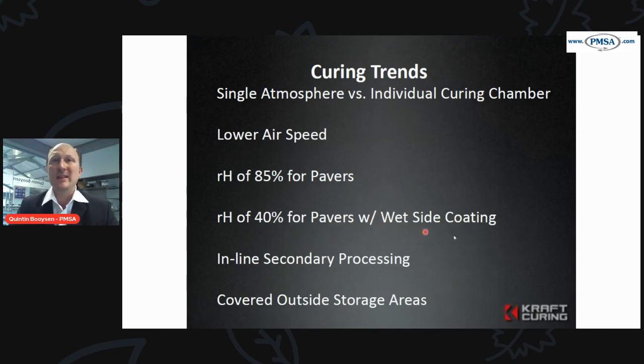We're also looking at wet side coating. So you may have a case where you want to wet side coat afterwards, a roof tile or a paver or something in the production process. And in that case, we can also adjust the relative humidity in an environment by putting in more heat in a closed environment and having a drier product exiting the system.